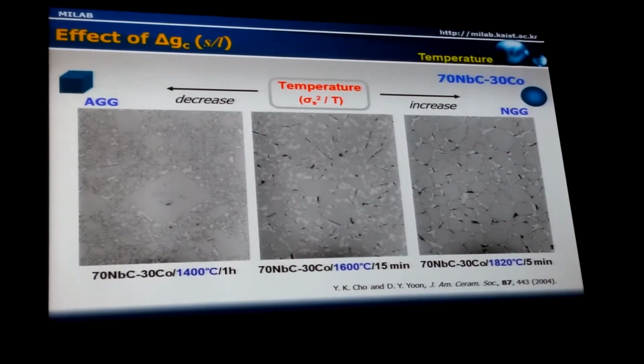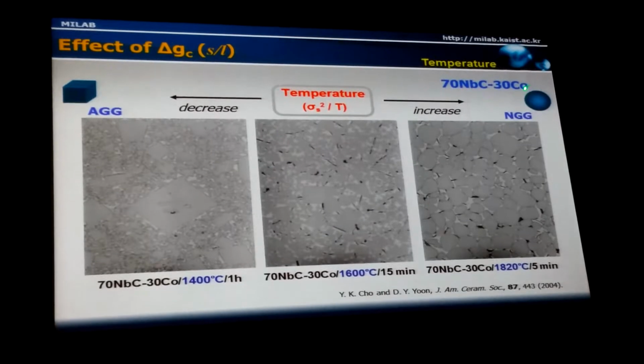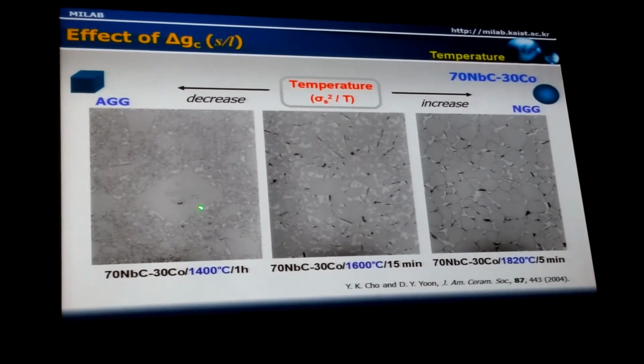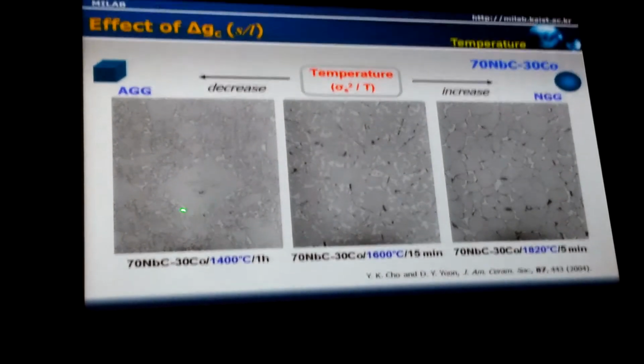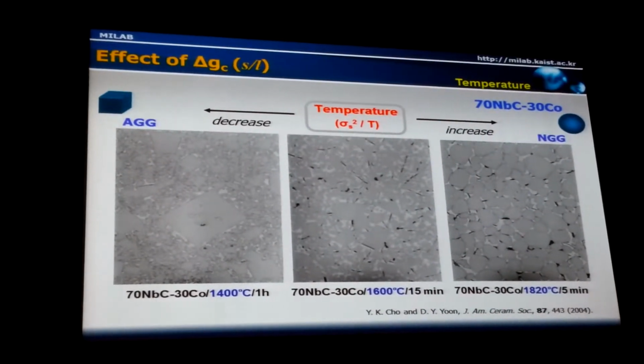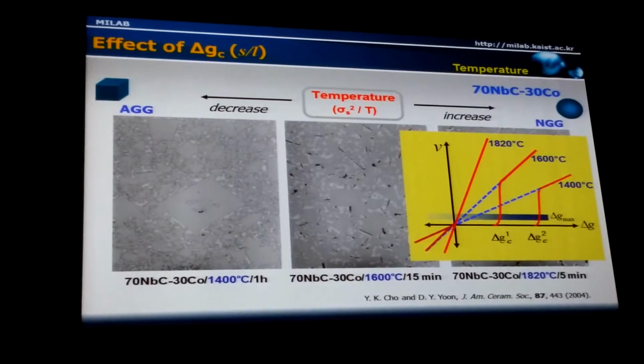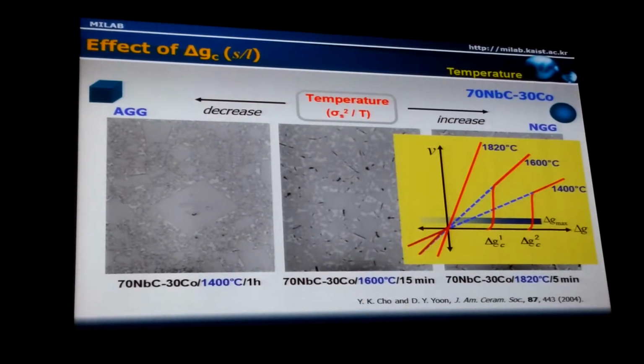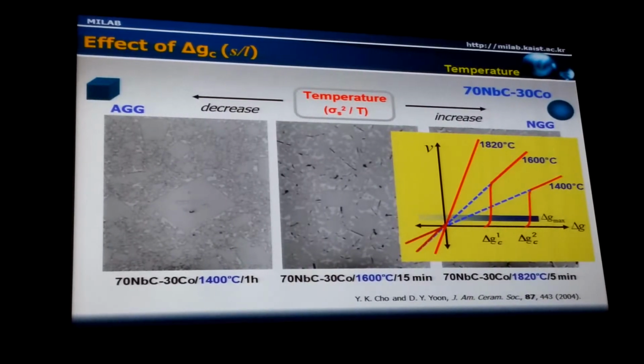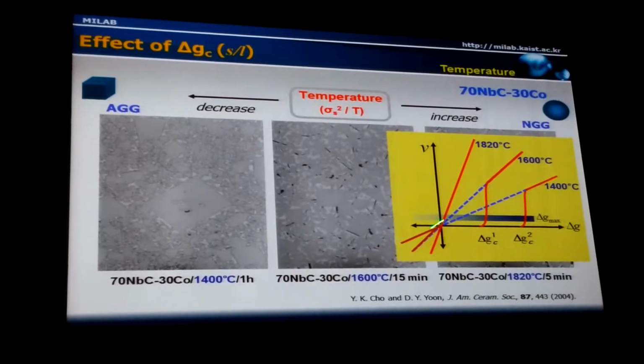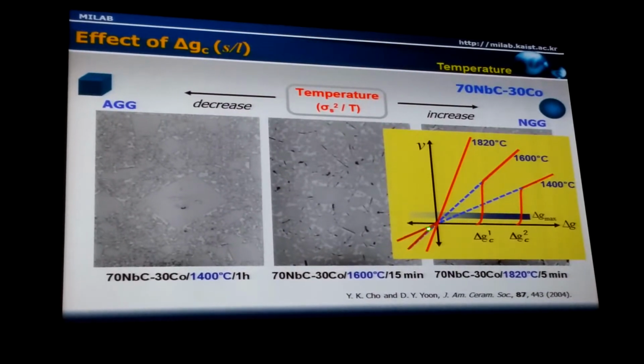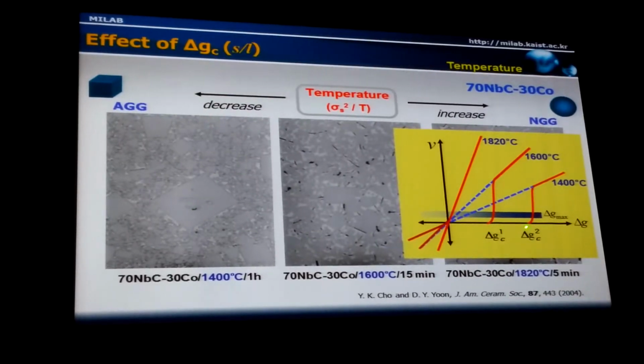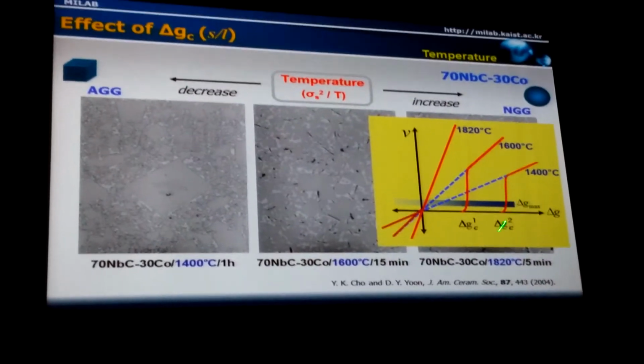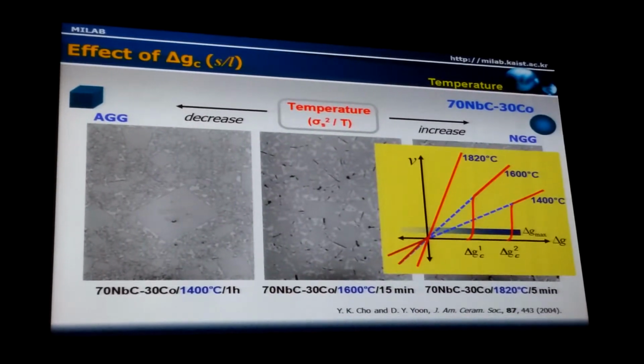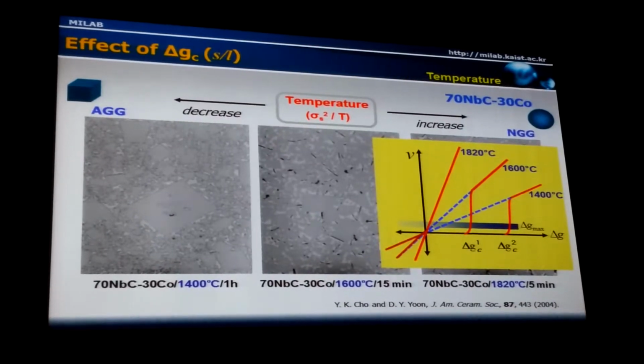And we also tested the effect of temperature. Here in this case, niobium carbide and cobalt. At low temperature, grain shape is faceted. At high temperature, grain shape is rounded. At low temperature, abnormal grains formed, and at high temperature, normal grain growth occurred. This observation is related to the variation of the critical driving force with temperature, because we started with the same powder, same composition. At high temperature, the critical driving force is negligible, but at low temperature, the critical driving force is considerable. And if the maximum driving force is comparable with the critical one, then abnormal grains form, as this left micrograph shows.